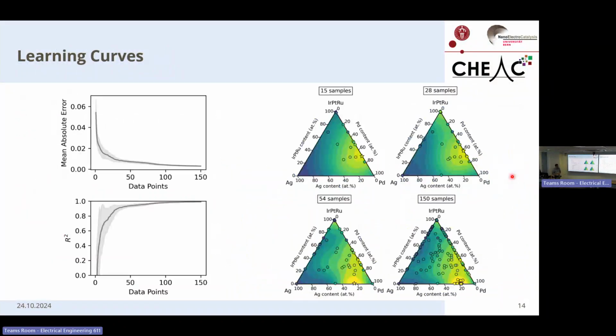The other thing that this work allowed us to do is to evaluate how well data sampled from Bayesian optimization can be used for machine learning applications. And for this, we can construct so-called learning curves. So the way we construct this is we take the data set as sampled by the Bayesian optimization, we fit a Gaussian process, and then we use this Gaussian process to predict the values of a known grid. And the difference between the prediction and the true values of the grid gives us an insight on how well the Gaussian process can reproduce the underlying DFT model.